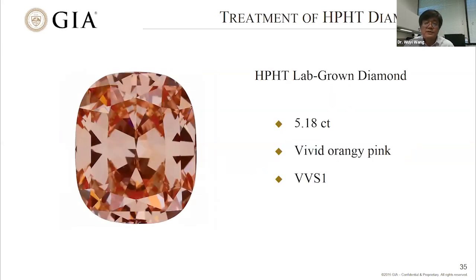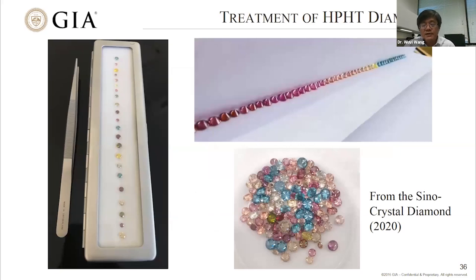This is one of quite a special diamond that we see in the laboratory, the orange color. Beautiful orange color is not very often seen. To introduce orange color is really difficult. This is an HPHT lab-grown diamond, very nice. It's a vivid orangey pink with a pretty strong orange hue, and that is over 5 carat. To us, it's rare to see an HPHT lab-grown diamond that can be treated to show strong orange color. So now we know there are quite a lot of lab-grown diamonds in the trade, and it means that quite often some of them are applied with a post-growth treatment.